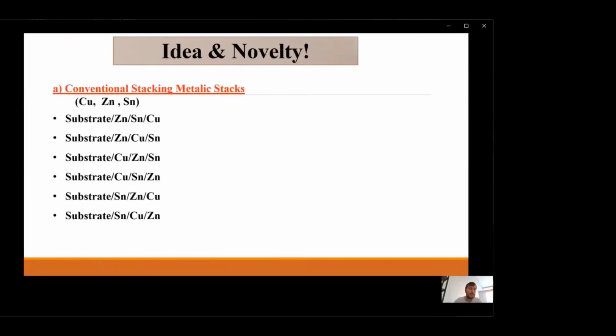What was the idea and novelty of this study? In the literature, you can see many different stacking orders. In general, the metallic layers can be deposited sequentially like this. You can see just a few stacking orders selected from the literature, but each stacking order has a big impact on the properties of CZTS thin films. So we should choose the most promising one in order to get high conversion efficiency.